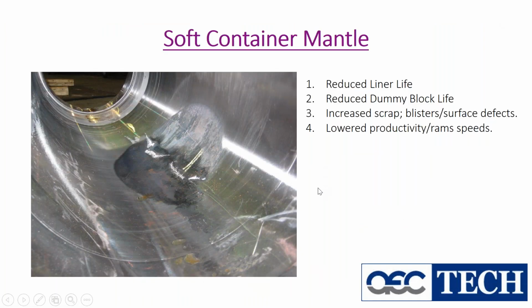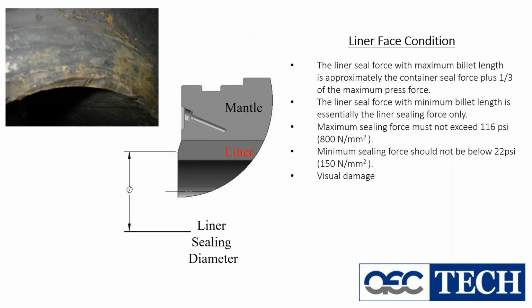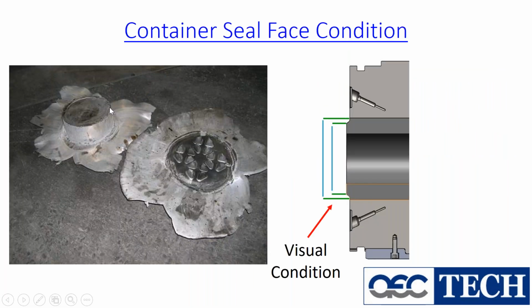Liner face conditions. With the amount of maintenance people that we all speak with, I don't know why that changed. We see people in production or production control, which is a bit of an oxymoron, moving dies. Let's move those dies from the 9-inch press to the 8-inch press, or the 8-inch dies to the 9-inch press. Just because the extrusion fits in the hole, that doesn't mean that that is what should be running on that press. The interface between the die and the ring and how it seals on the container is so critical. If the ring and the die infringe on the area, which is in most manuals, or you can talk to your die maker, your tool maker, that is going to teeter in here and chip away at this edge. As soon as you lose this seal, trouble with a capital T.